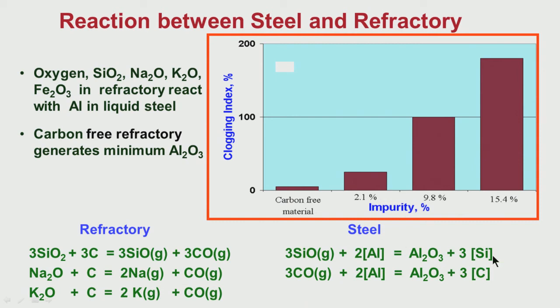in liquid steel. Similarly, carbon monoxide will react. How is carbon monoxide forming? It is forming from the carbon in refractory reacting with SiO2, with sodium oxide, with potassium oxide. If these constituents are present in refractory, SiO2, sodium oxide, K2O, similarly Fe2O3, some examples I am giving, the carbon in refractory will react with them and generate SiO and carbon monoxide. So, carbon monoxide generation is bad, SiO generation is bad, because they will react with aluminium in steel and form alumina. So, the alumina